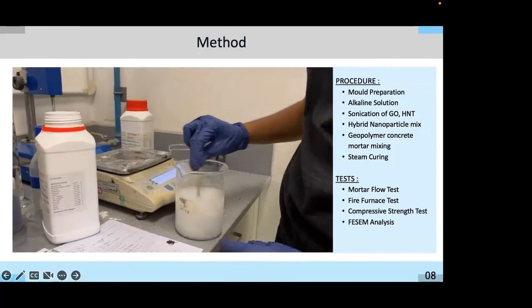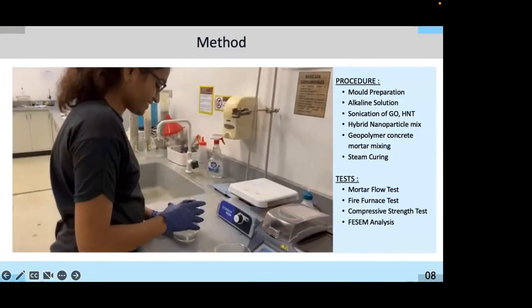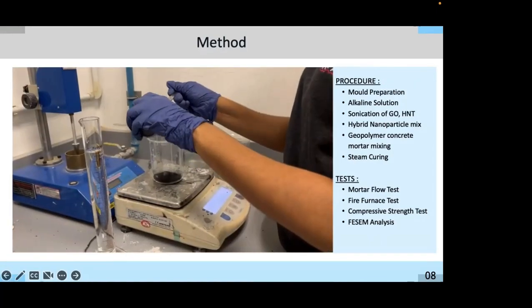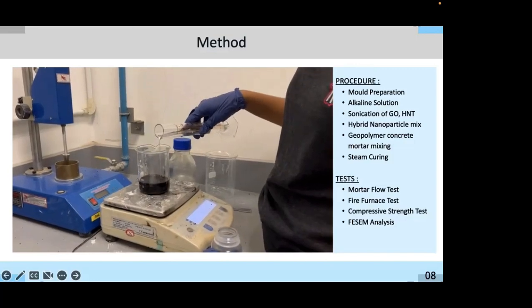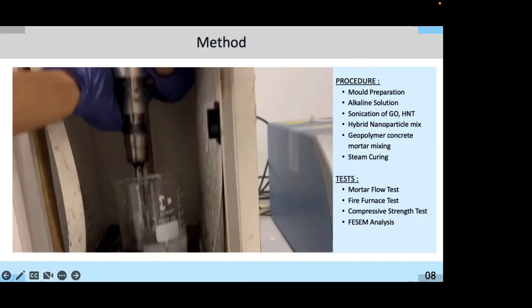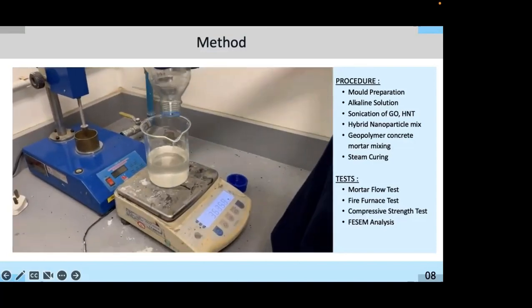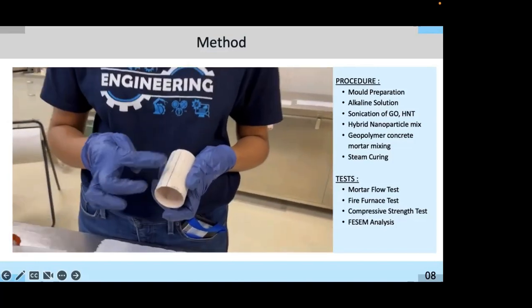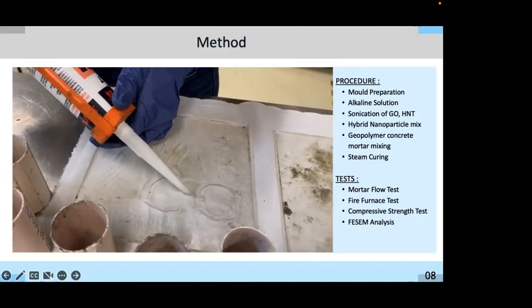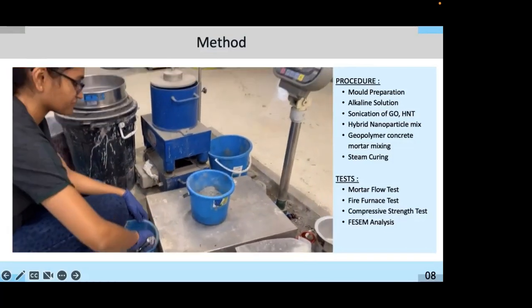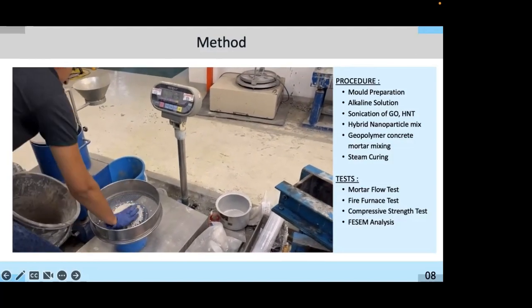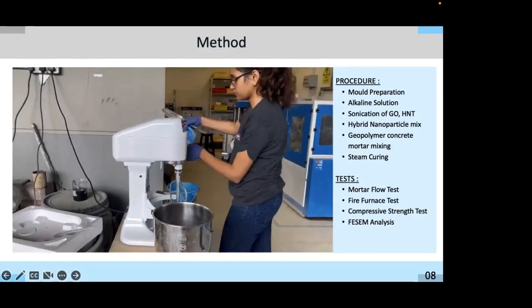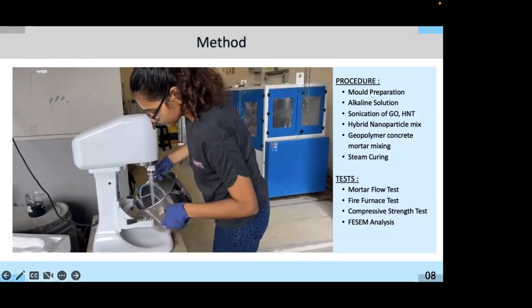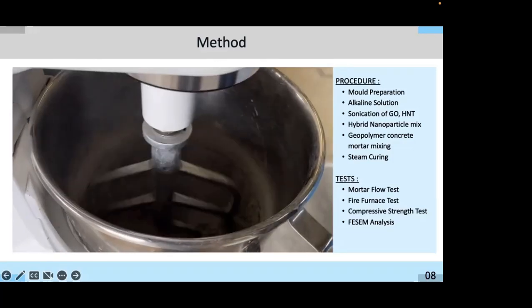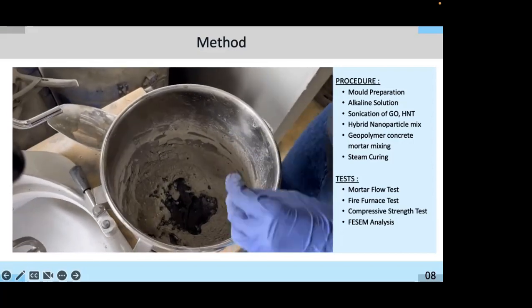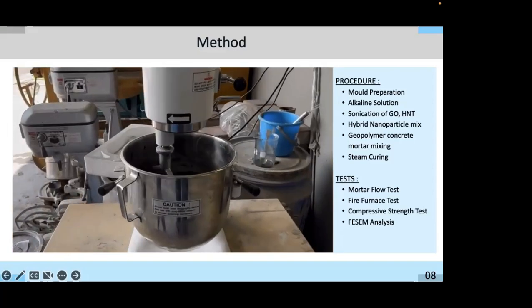So you can see here the process of getting the alkaline solution prepared, and then they introduce the graphene oxide and the halloysite into the mixture. We've done several processes of sonication of the material to try and see whether that actually helps. This is a grad student preparing the molds for casting. This process is just preparing the materials and the raw ingredients right here, your typical geopolymer mix design. It's being mixed, and then of course here's where we add the chemicals and also the nanomaterials in there.